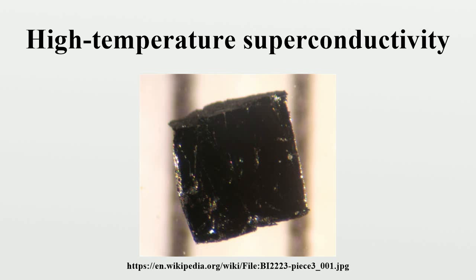The Bi-2212 phase appears only after a few hours of sintering at 860 to 870 degrees Celsius. But the larger fraction of the Bi-2223 phase is formed after a long reaction time of more than a week at 870 degrees Celsius. Although the substitution of Pb in the Bi-Sr-Ca-Cu-O compound has been found to promote the growth of the high Tc phase, a long sintering time is still required.